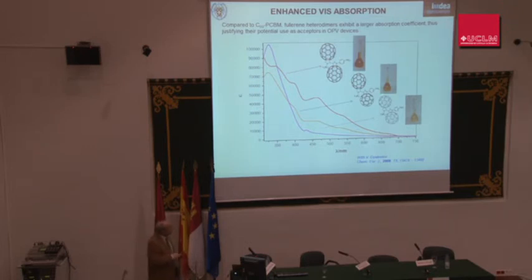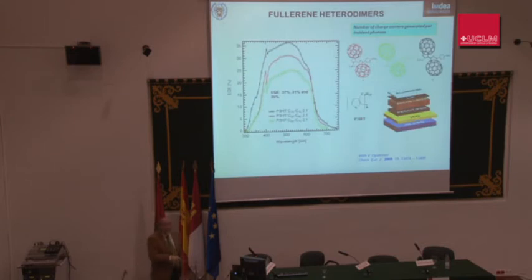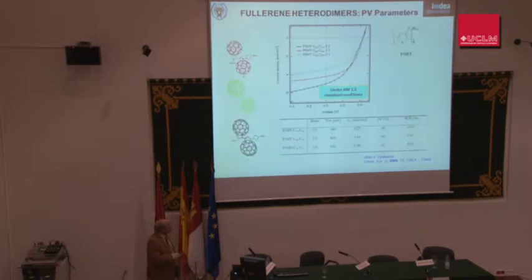So we decided to carry out a study with these dimers. It was a little bit disappointing because, despite the very good absorbance of the C70 dimer, you can see here that the external quantum efficiency was in very good agreement with that found for the absorbance of these systems. This is with the poly-3-hexylthiophene. But when you have a look at the efficiencies, they resulted to be just around 1% for these systems, in particular for the C70. These were not the expected results.